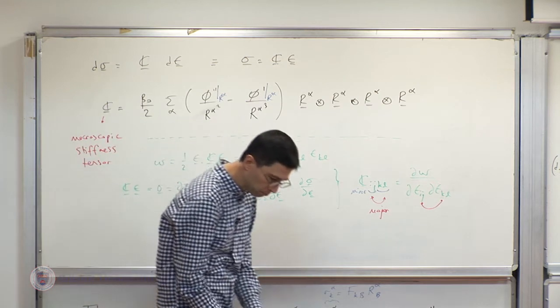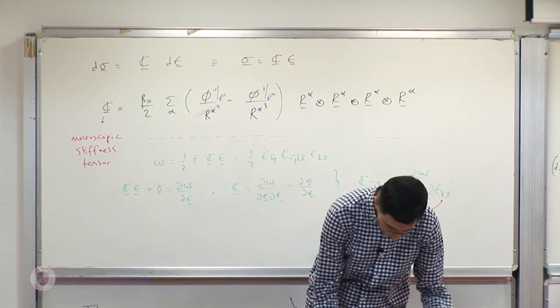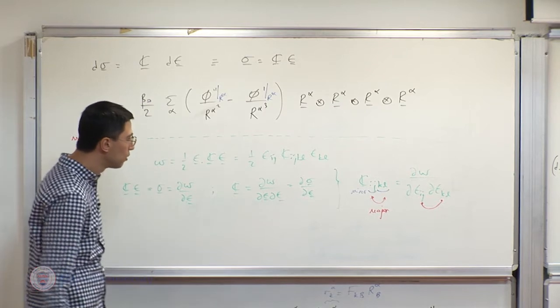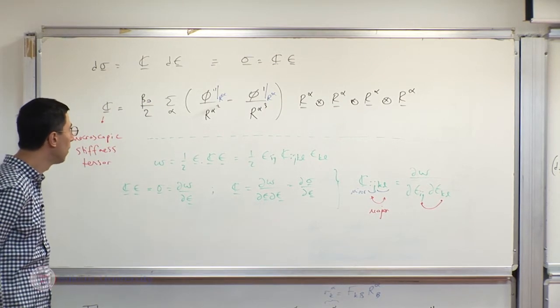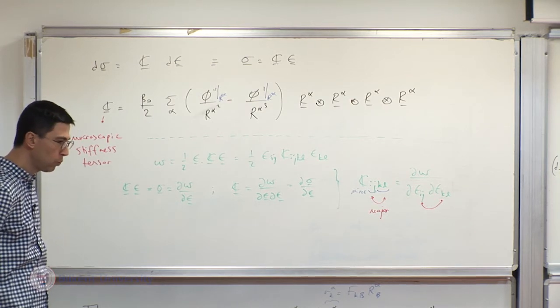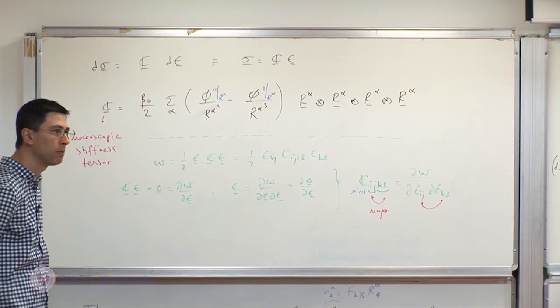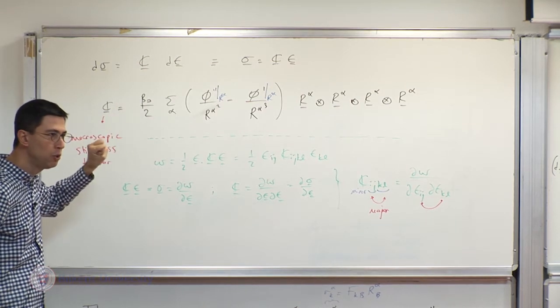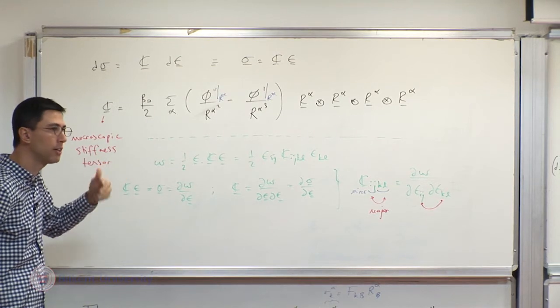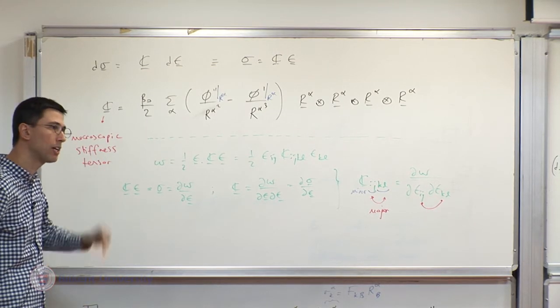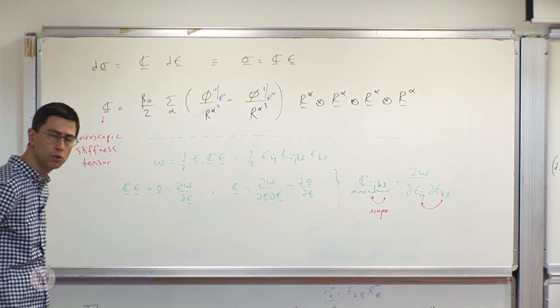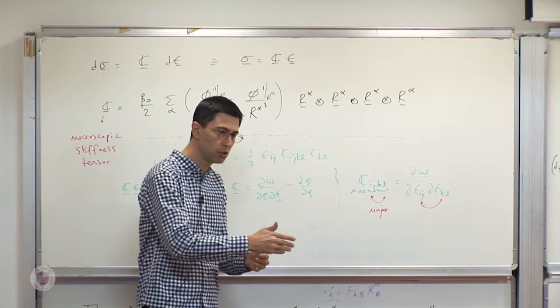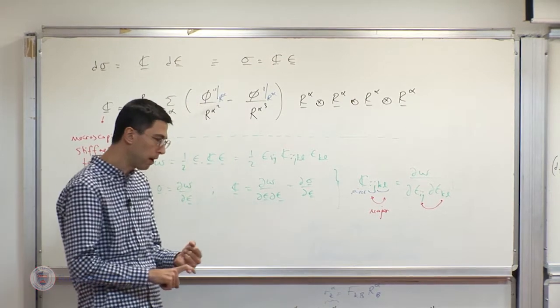We have come quite a long way. Let's take this idea, pick an example, calculate the macroscopic stiffness tensor, look at its components, deduce parameters such as the shear modulus, and compare with experimental data to see how well the result is doing. We have to realize we've made a number of assumptions: pair potentials and the Cauchy-Born hypothesis, which are strong assumptions.